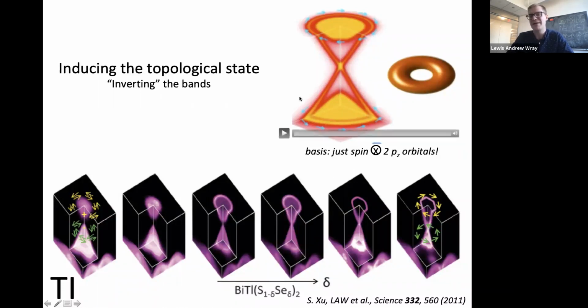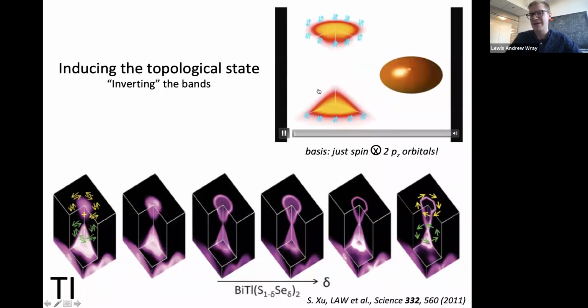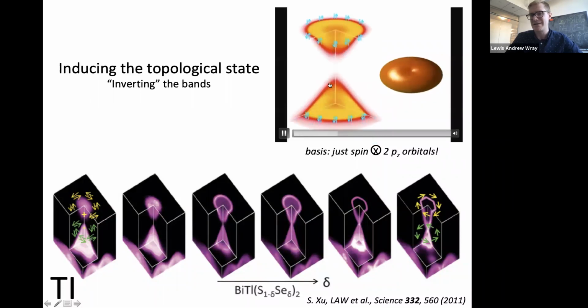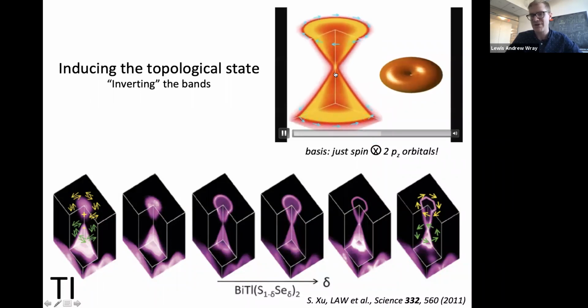When we created this paper, I did a little quick model of it. This is an image of its momentum on the in-plane axes and energy on the vertical axis. You have bulk states that are sort of shaded in at top and bottom, and surface states that cross from the bottom continuum of bulk states to the top continuum. This is taking the simulation from a trivial regime to the non-trivial regime where you have topological surface states.